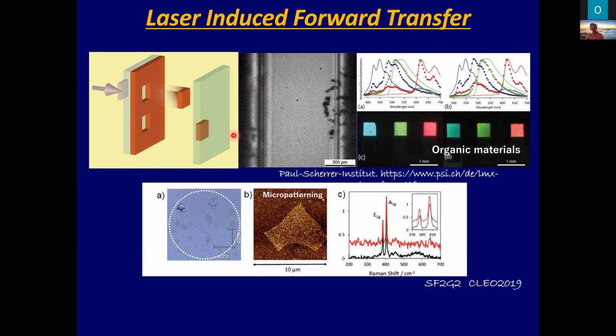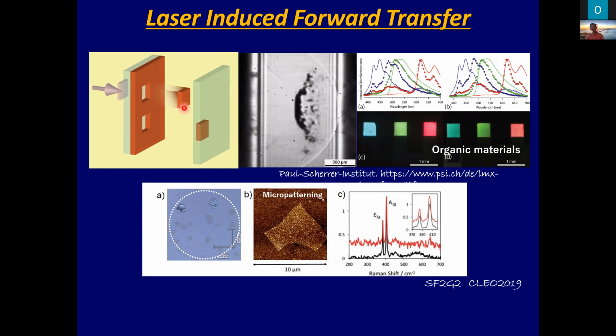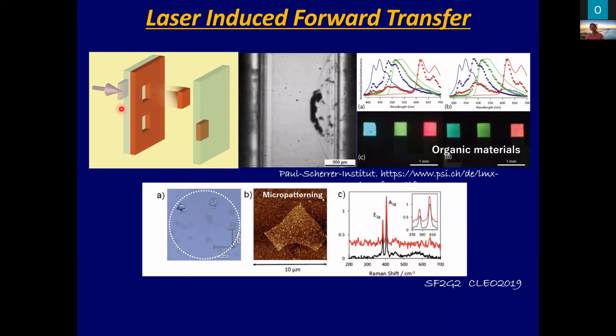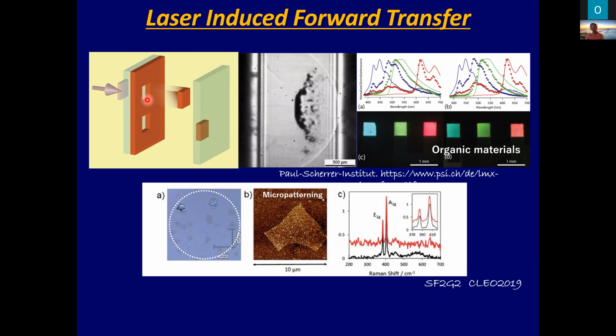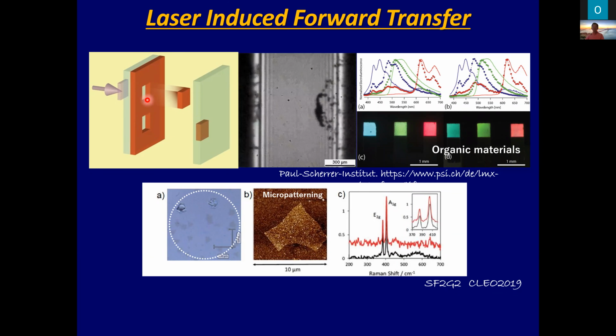For example, we prepare the donor thin film. This donor thin film is pumped by the laser from the backside. The donor material breaks into fragments, and the fragments fly away. We catch a fragment by using the receiver substrate, so that we can pattern the donor material two-dimensionally.